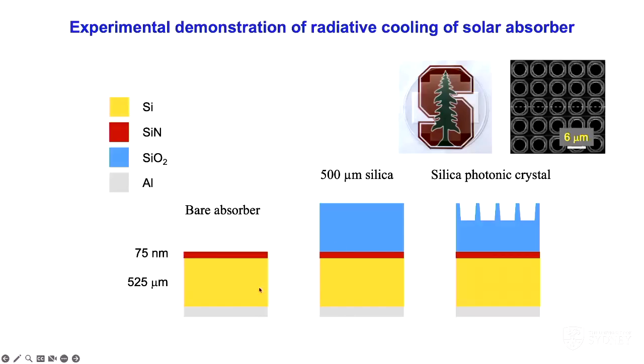The absorber that we use is a piece of silicon, the type commonly used in solar cells, with an anti-reflection silicon nitride layer. That's our bare absorber. Then, to do radiative cooling on this absorber, we consider two structures. For one of them, we put just a thick layer of silica on top of it. As I mentioned, silica has radiative cooling characteristics. For the other structure, we further put what we call a photonic crystal structure into the silica, a structure with a periodic array of air holes introduced in it. This silica photonic crystal structure is visibly transparent. Here is a demonstration: we put this structure on a Stanford logo, and you can still see the logo. And there's no color associated with it either.